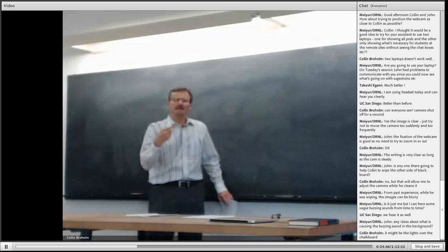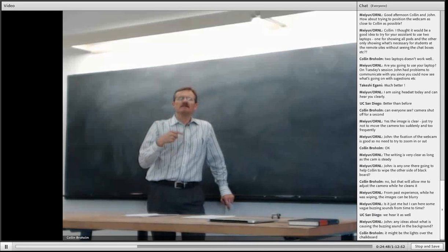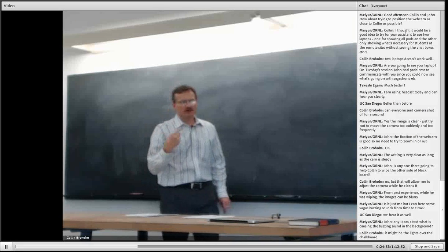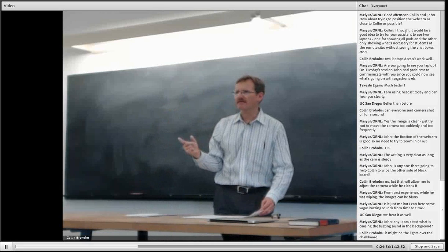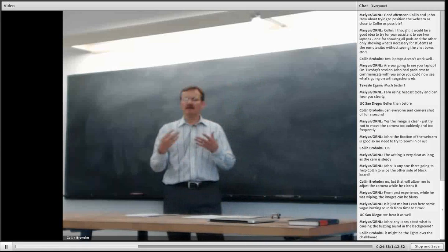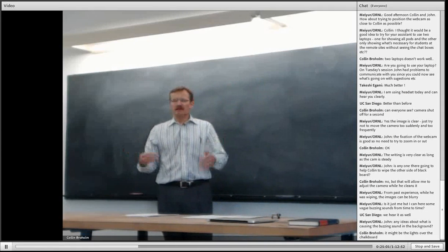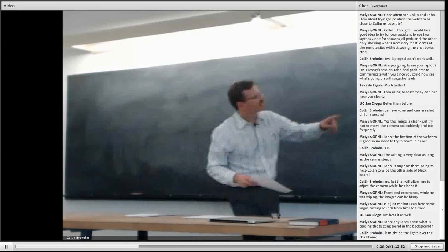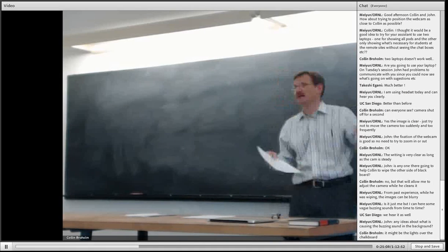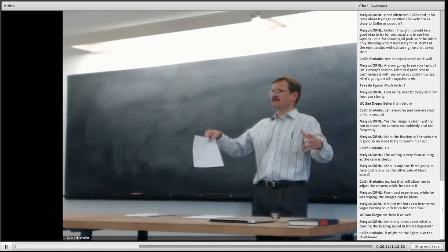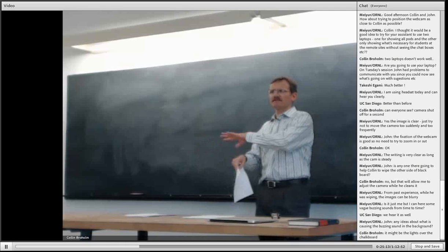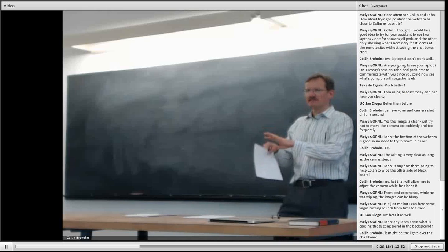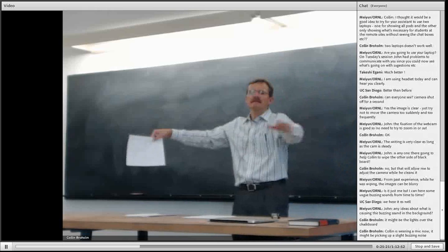That would certainly assure the limit that I would like to be in. To be more specific, the limit I would like to be in is the one in which I have no inter-particle interference terms. This would certainly be assured if I have a sufficiently long wavelength, but it can also be assured by the particular geometry that I'm dealing with. Suffice it to say that I want to treat my forest of delta functions, because that's what I get when I have a solid with a lot of these nuclei sitting in it, as basically a smeared density. So I'm going to neglect the fact that they actually are in certain locations and just think of the whole potential as being completely smeared out in space.